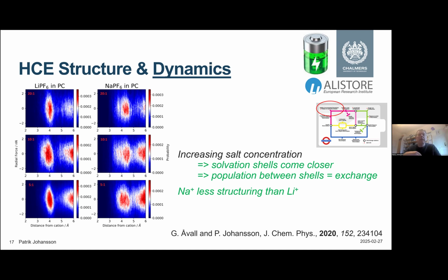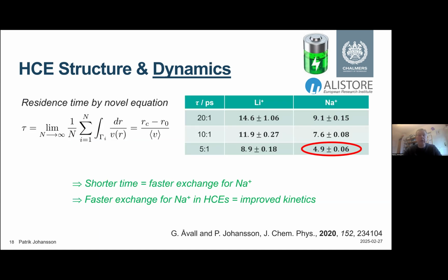But really, for the sodium case, there is also an exchange between the shells. You see the probability, especially for the highly concentrated, that you have species in between the shells. And that really means that you have a solvent exchange. So you have some kind of dynamics between the shells. And having that knowledge and the mathematics behind that, you can actually start to look at the residence time of these solvents. And from this system, we also developed a new equation for the residence time.